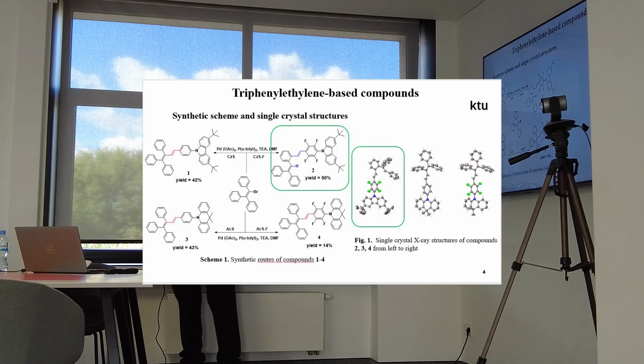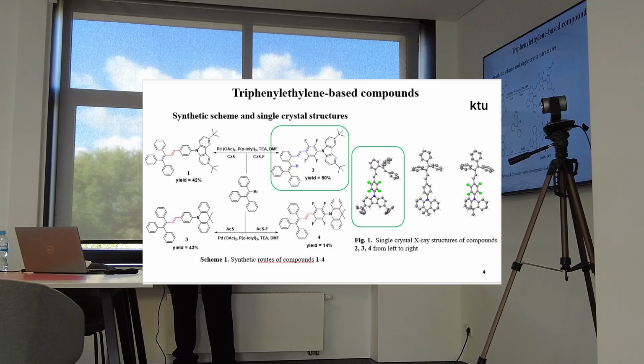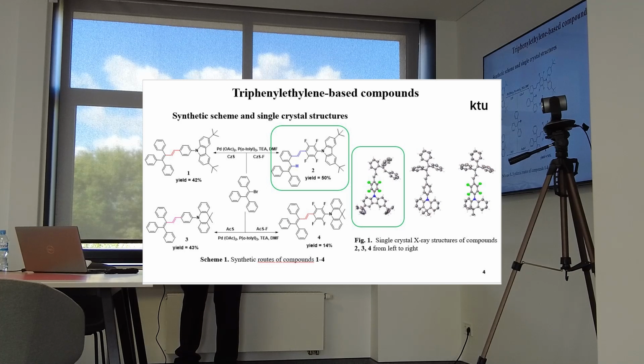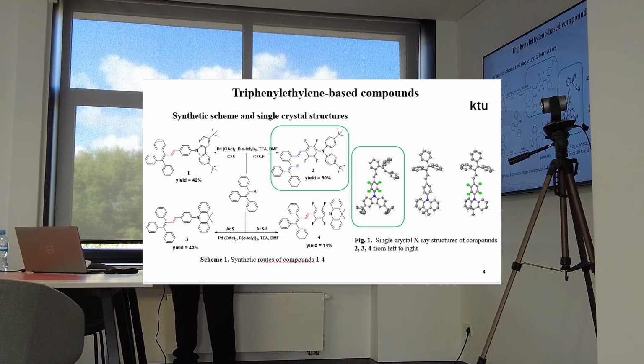The first series of materials is based on triphenylethylene compounds. The target materials 1 to 4 were synthesized in a two-step synthesis process. In the first step, for compounds 1 and 3, Buchwald-Hartwig reaction was used to acquire the intermediates, and for compounds 2 and 4, nucleophilic aromatic substitution reaction was used to acquire the intermediates, and in the final step, Heck coupling was used to acquire all the target compounds. The structures were confirmed by NMR spectra as well as single crystal measurements, and for compound 2, we can see that an unusual cyclopalladiation was observed, and this was confirmed by single crystal analysis.